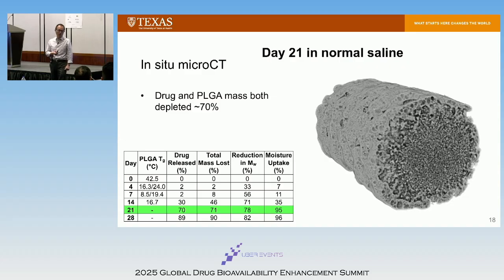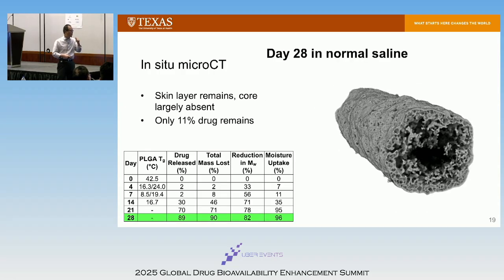Siepmann's group in Europe did a lot of study. They found there's a critical molecular weight threshold when those oligomers can actually dissolve and diffuse out. So we're dealing with this skin and core phenomenon. And that's what causes this unique phenomenon where the polymer degrades, but the drug is not coming out until much later. At day 28, most drug is gone, and you still see the skin effect. At this point, the skin is very porous.